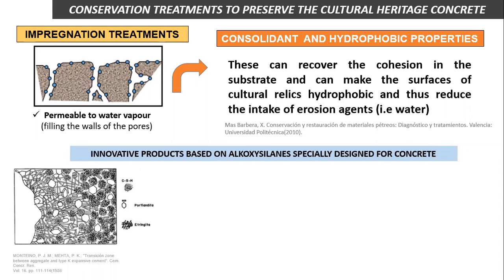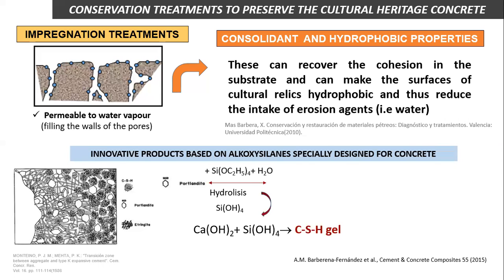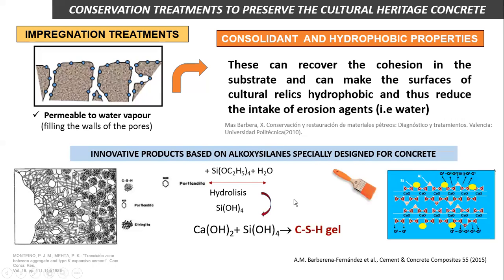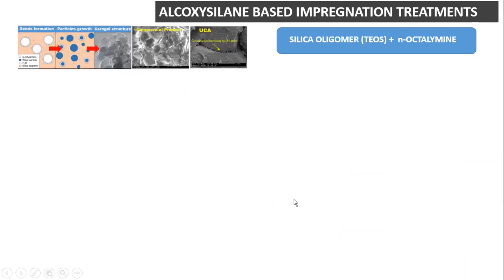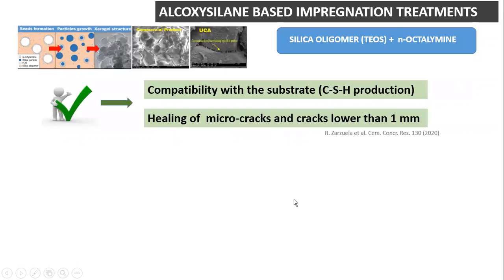Under this InnovaConcrete European project, we are developing innovative impregnation treatments specially designed for concrete. These treatments are based on alkoxysilanes, and the novelty is that they are able to react chemically with the substrate, with the concrete, especially with the Portlandite, to produce silica gel. The advantage of these treatments is that, due to the silica gel production, they are going to be 100% compatible with the original substrate. And what is more, they are able to heal microcracks and cracks lower than 1 millimeter.